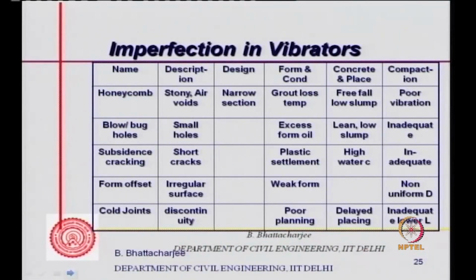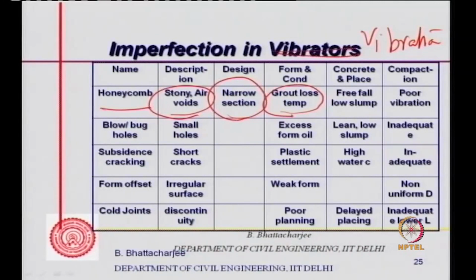Right. Now, imperfection in vibrations, honeycombing. Imperfection due to poor vibration, essentially. In vibration, you can say concrete vibration. Honeycombing, if you have not done the vibration properly, it will have stony and air voids. It can generally happen in narrow sections, and grout loss can also cause this if the forms are not joined properly. Free fall, low slump concrete, this is a concrete type, and poor vibration can result in this.